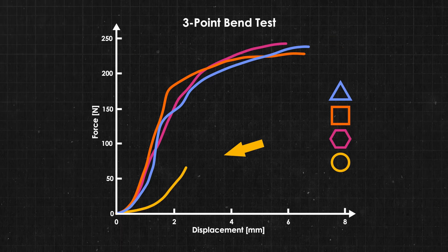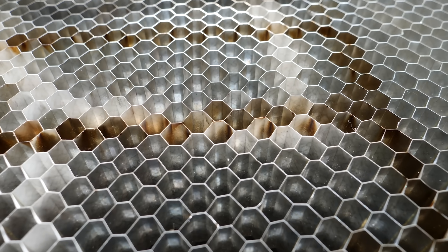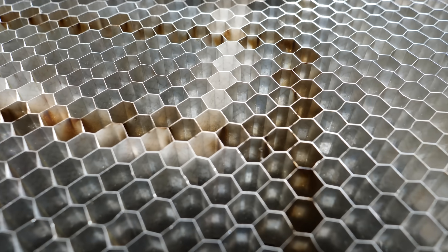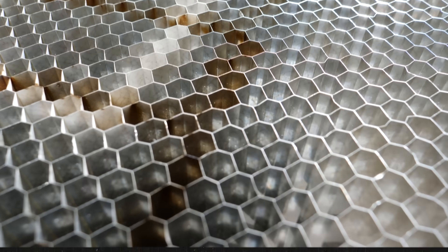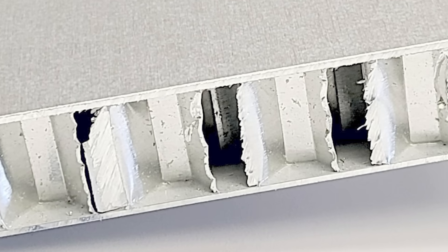When I plot it against the other samples, you can clearly see that any kind of connected infill, regardless of shape, is going to give you about a 350% increase in your ultimate strength. At least for this configuration. Whether this would hold for something like aluminum honeycomb or aluminum composite honeycomb is another question entirely. Especially because the infill there is much thinner relative to the thickness of the plates.